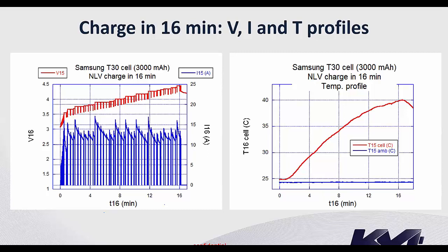Now we go to 16 minutes. So the voltage here is close to 4.5 volt, okay, which by the way is higher than what Samsung is recommending. Samsung recommends that we should not exceed 4.2 volt, but in our case, if we use NLV, the fact that we are using higher voltage doesn't affect much the life of the battery and its safety. So in this case, the temperature goes to 40 degrees when we charge the battery in 16 minutes.